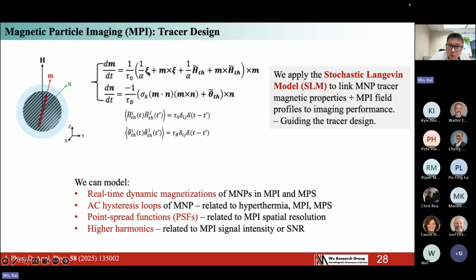So the H contains the time varying magnetic field and also the anisotropy equivalent field. And we also consider the thermal energy at a finite temperature. We convert it to a thermal equivalent magnetic field, H_th. Based on this, we also involve the thermal noise into the nanoparticle system. We can accurately estimate the dynamic response of the nanoparticles in suspension solution. We can plot the real-time dynamic magnetization of these particles for imaging or MPS bioassay applications. We can also get the AC magnetization loop of particles. We can also plot the higher harmonics and point spread functions that guide the spatial resolution of the MPI imaging.